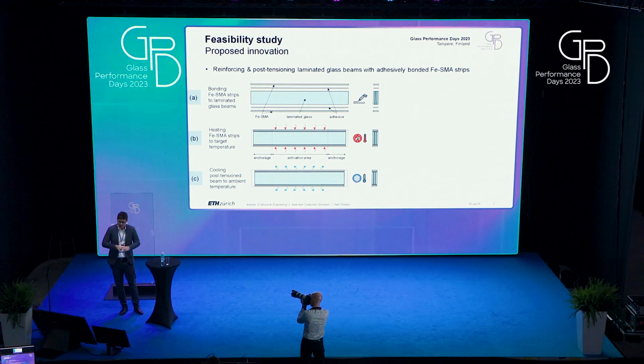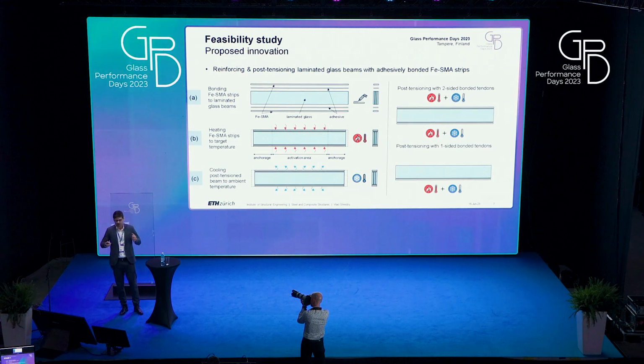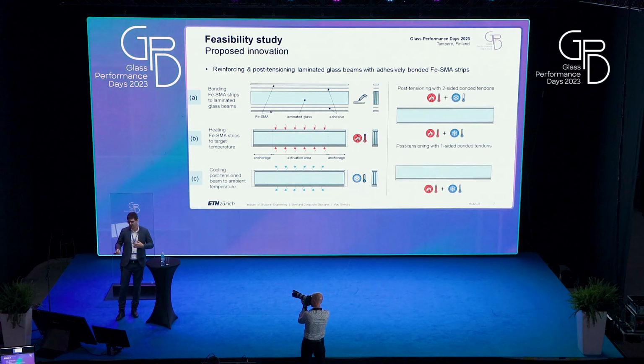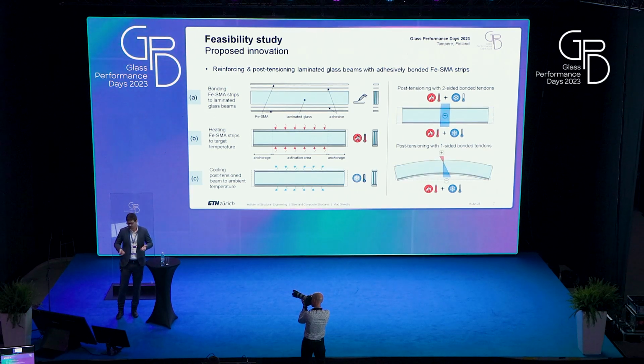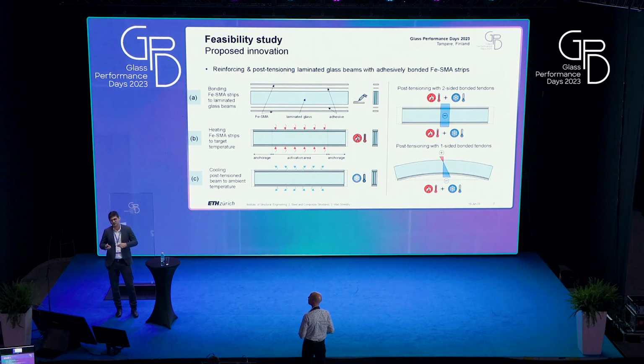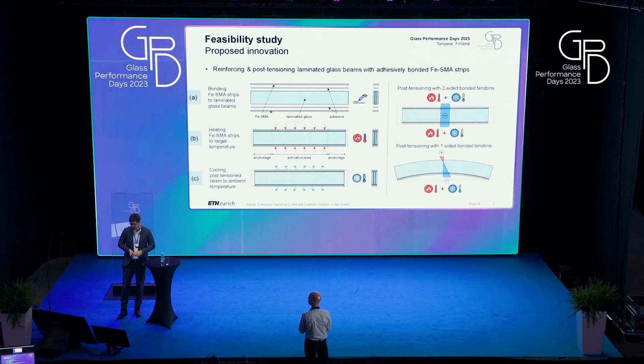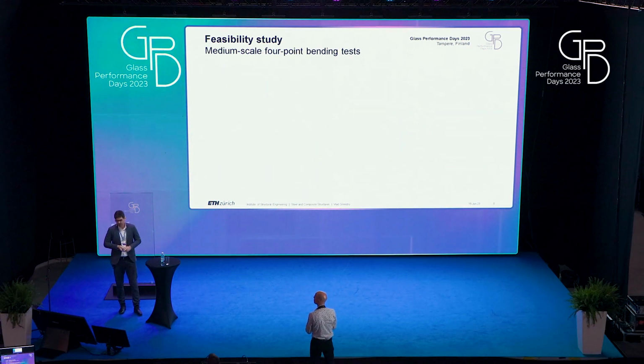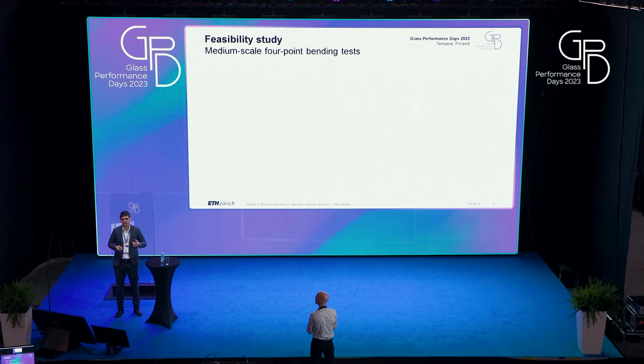Of course, as I mentioned in the introduction, depending on your loading situation, you could apply the strips along both edges or only along one of the edges. This would result in a different pre-stress state, with a uniform stress or with a linear stress distribution. I will now present some results from the bending tests that we performed. We looked at medium scale tests, mainly for cost reasons, and also because it was a feasibility study.